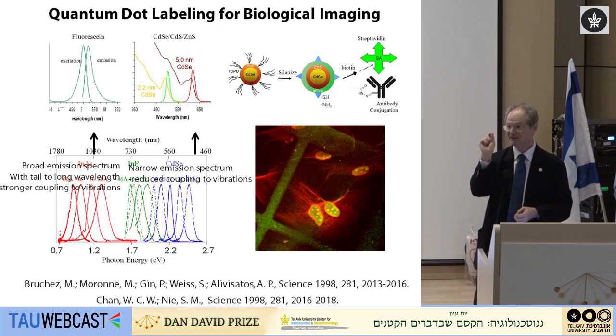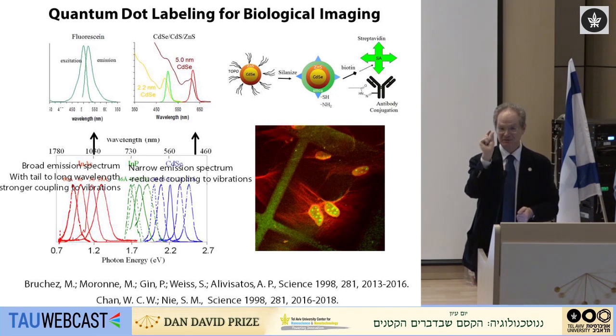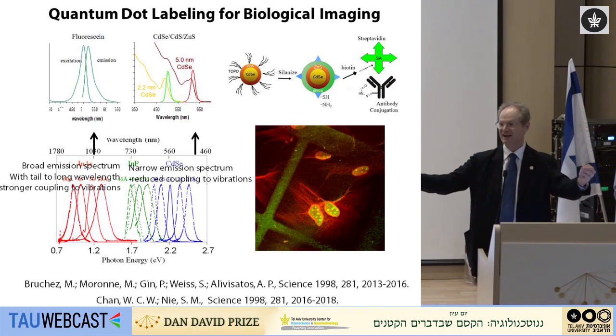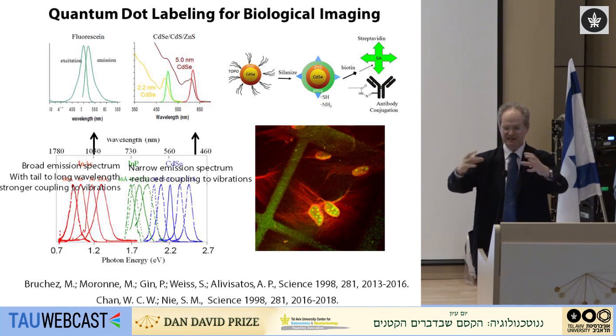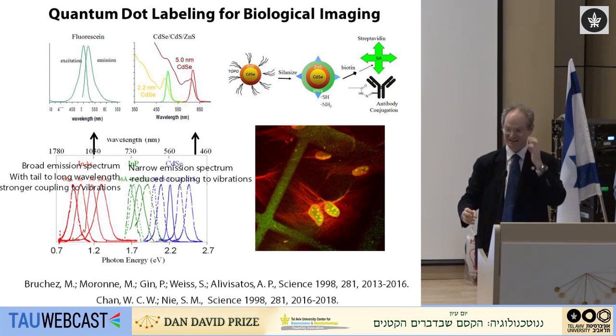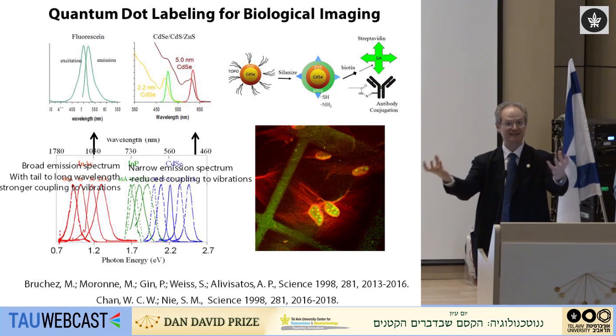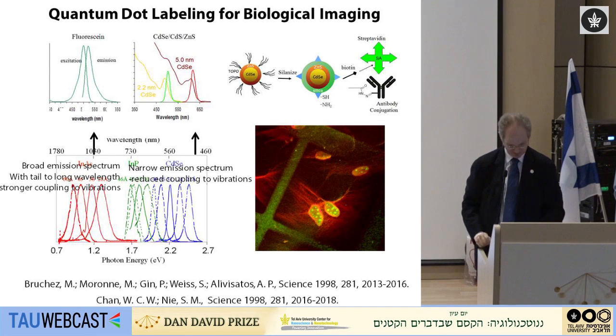The light that comes out is spectrally more narrow in energy because in the organic dye, when the excitation takes place, all the bonds change a little bit. The molecule essentially changes its configuration. And then when it comes back, again, there has to be another change. So that alternation of structure broadens the spectrum out. And the quantum dot, in contrast, has a much narrower spectrum.